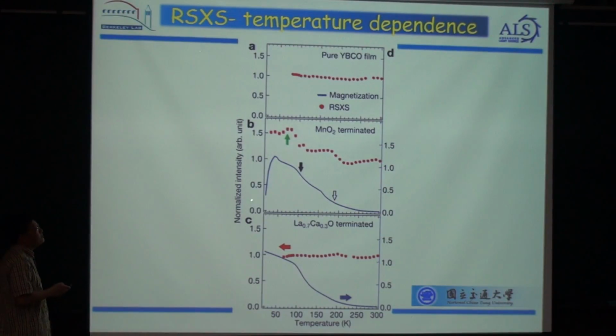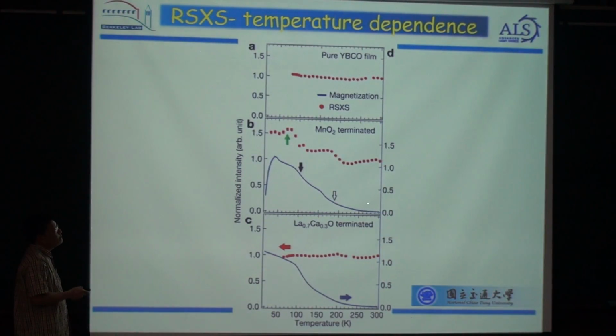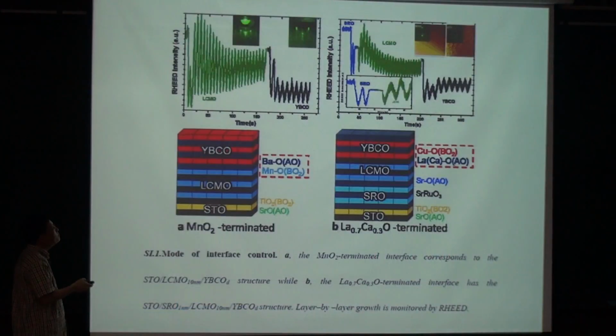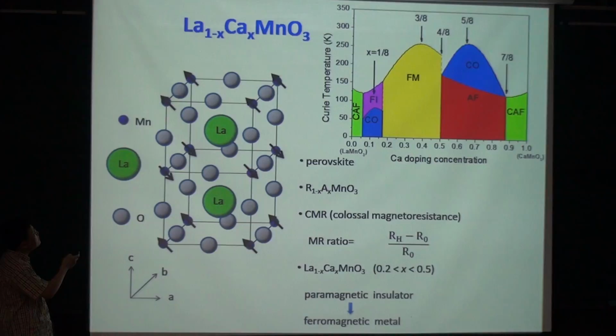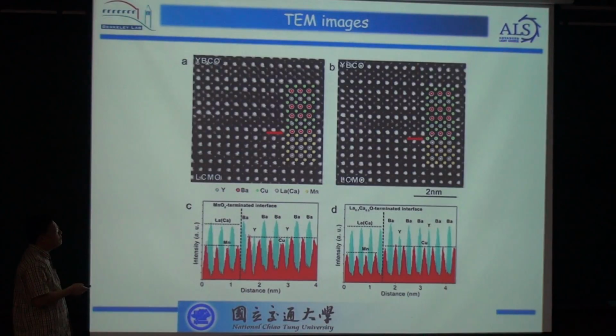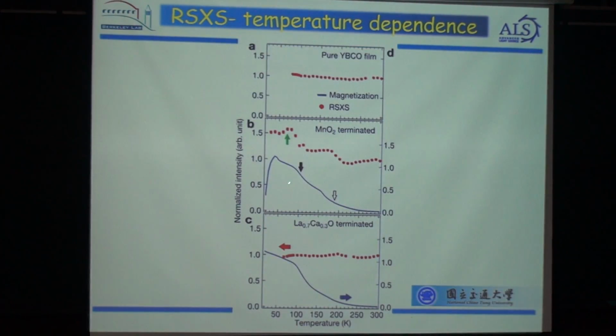So we measure the magnetization of this sample. So this is a magnetic data. We find out that there is a magnetic transition happening in this sample, and presumably it is because LCMO is a ferromagnetic material. This magnetization measurement actually represents some ferromagnetic transition, and this new order simply coincides with the magnetic transition in LCMO.